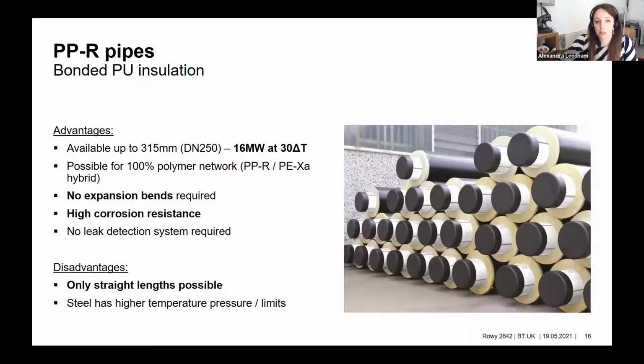PPR pipes are also large pipes, but in polymer. PPR stands for reinforced polypropylene. This is also the same insulation as steel, polyurethane, and in general, it's available up to 315 mm in diameter. So in steel equivalent, it's DN 250. But these kinds of pipes can be manufactured in slightly larger diameters too, as a custom. So if you would like to have a combination of, for example, PPR pipework and another type of polymer like PEX, you can have a hybrid system between these two to create a fully polymer system on a larger level.